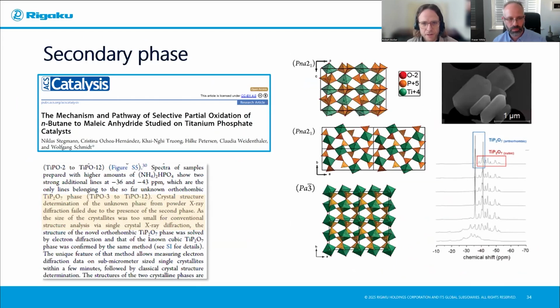For inorganics, like here for this catalyst, it's a similar situation, and for minerals, for example. It's just impossible to grow larger crystals, of course, and you often have multi-phase examples, and getting the phases out from powder diffraction patterns is often prohibitively difficult. And with electron diffraction, because you screen this grain by grain, you find it out straight away.